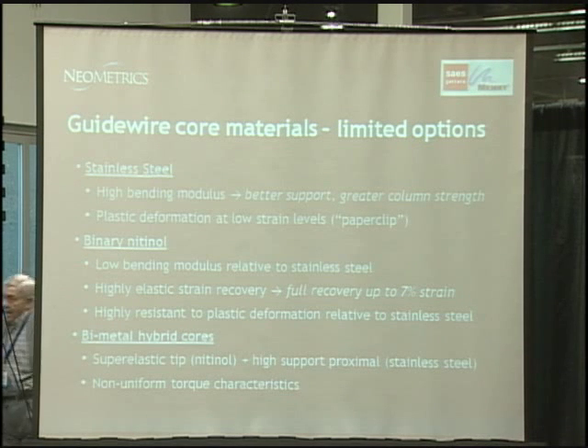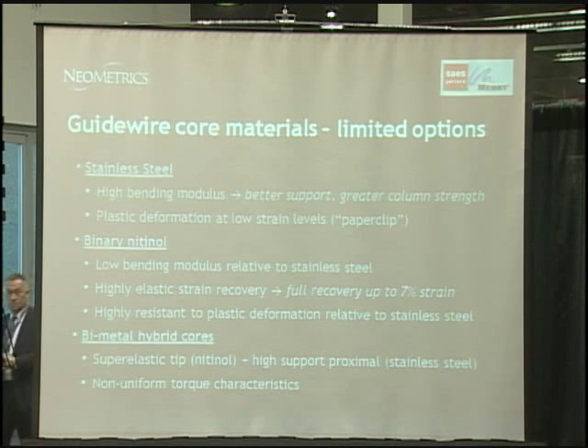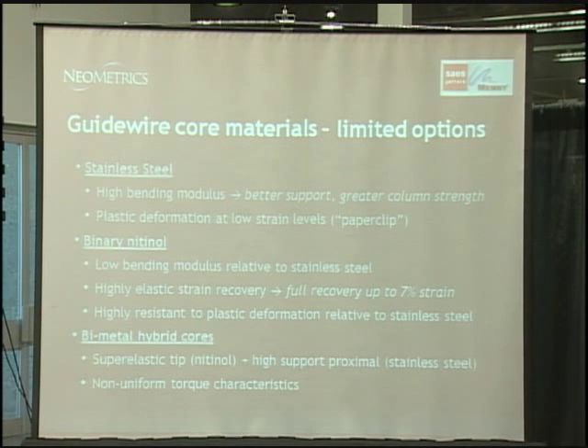Thus far, the selection options for guidewire design have been fairly limited. We've had a choice between stainless steel and binary nitinol. The advantage of stainless steel is that it has a very high bending modulus, very good for support, especially for small diameter wires. Has great column strength, very pushable, but it deforms at very low strain levels. In other words, the material, once it's been deformed, it cannot recover to its original shape.